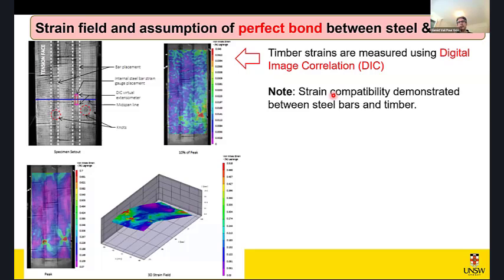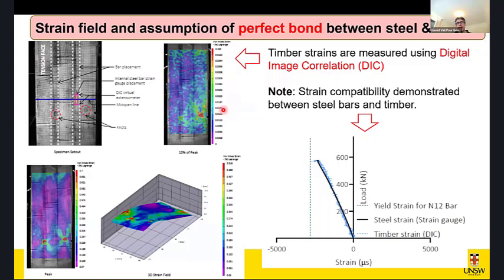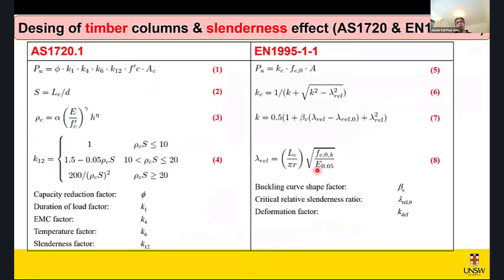And to basically establish the bond and see what's the bond behavior, we just use the DIC on many specimens, columns, and beams, and also we install the strain gauges on the steel bars and compare the strain in timber with strain in steel bars to see whether there is any difference or the difference is small, and hence we can assume there is a perfect or near perfect bond between steel and timber. And this is one sample graph. You could clearly see timber strain from DIC is the blue one, and the steel strain from strain gauge is the dark solid black line. And you see very close correlation that clearly indicates there is near perfect bond between steel and timber, and that would basically pave the way for adoption of some simplifying assumption in the process of development of